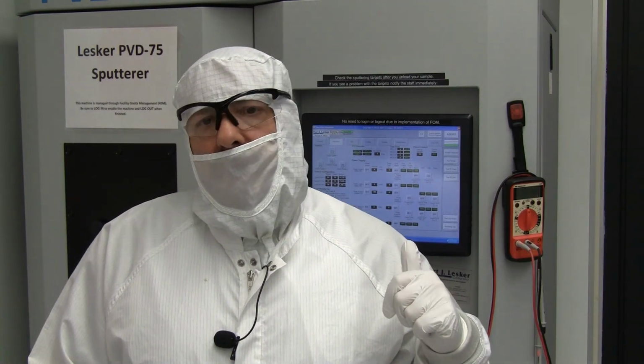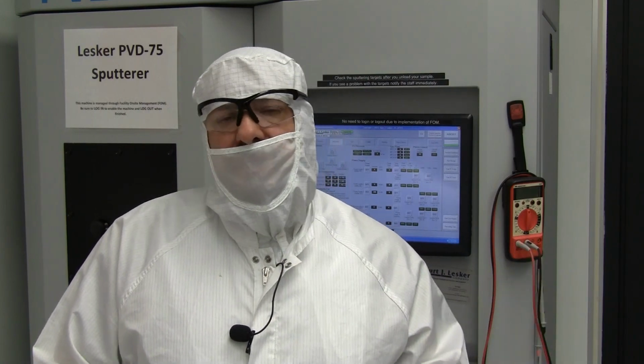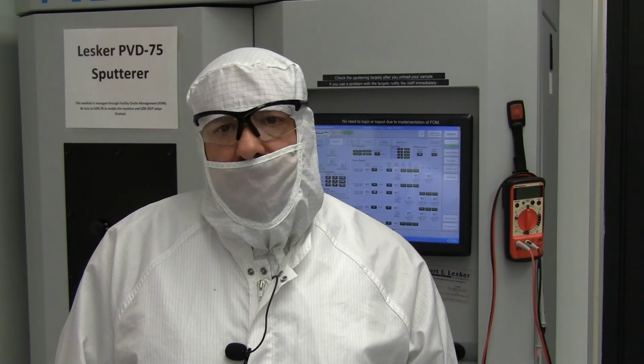That is, sputtering and evaporation both produce a lot of defects. Even on pro level tools like this, you end up with voids, dislocations. You never make really crystalline materials using this process. So a lot of times you want to be on the low side of the pressure range to try and make your films as perfect as possible. They will never be perfect. Defects will follow, stacking faults. Sorry for the jargon, but just shorthand for your films are never perfect and they often have pinholes.